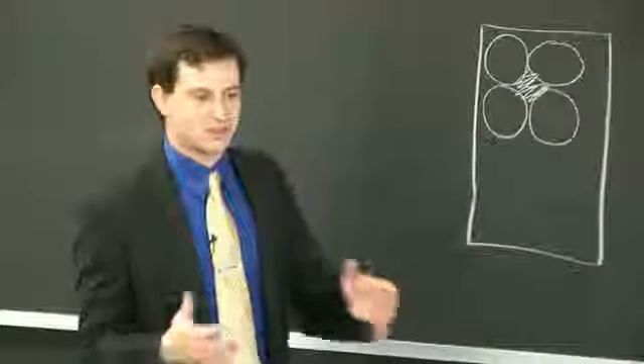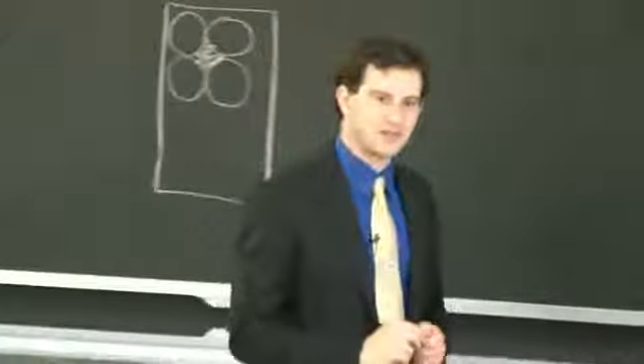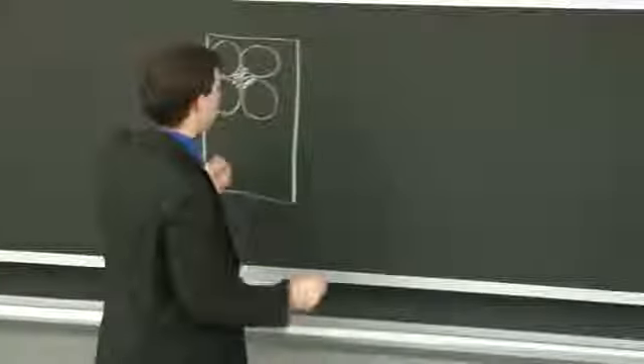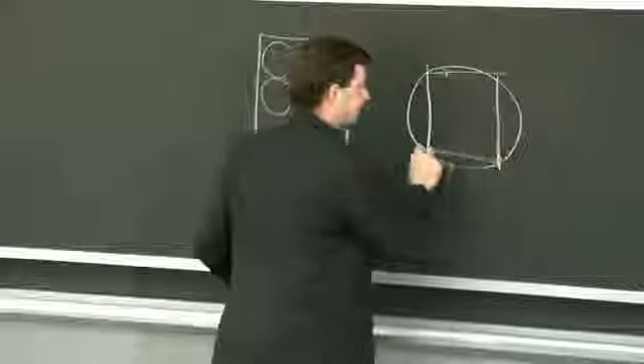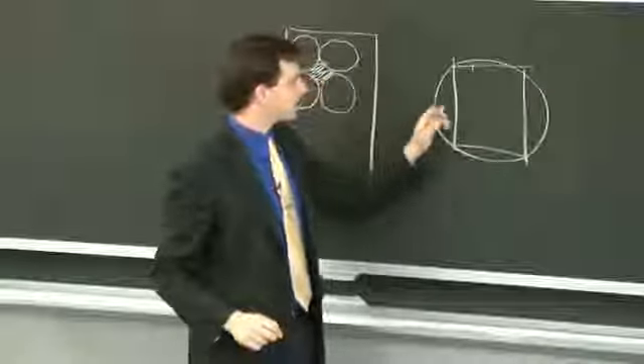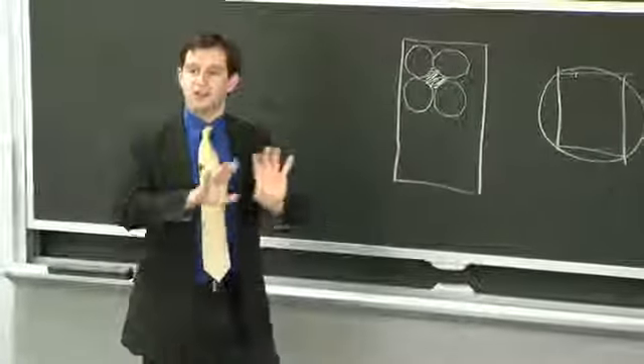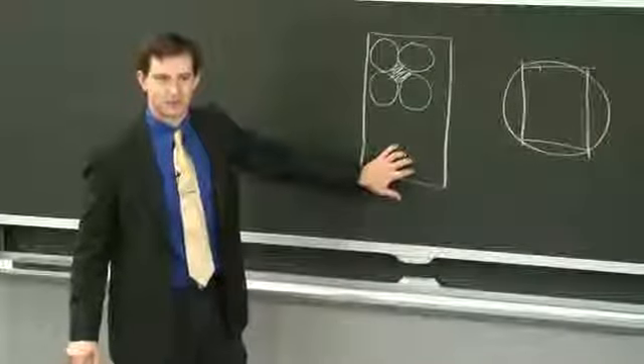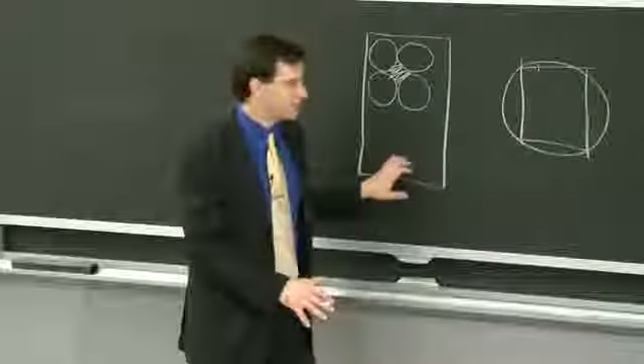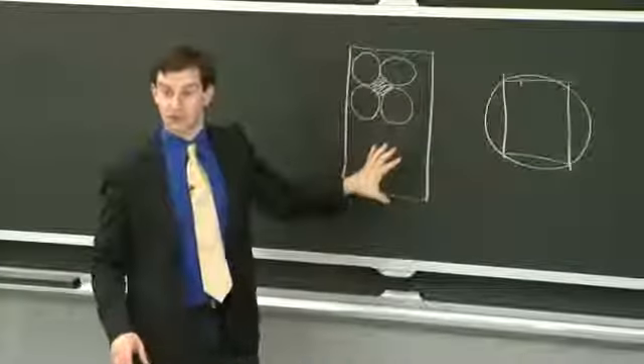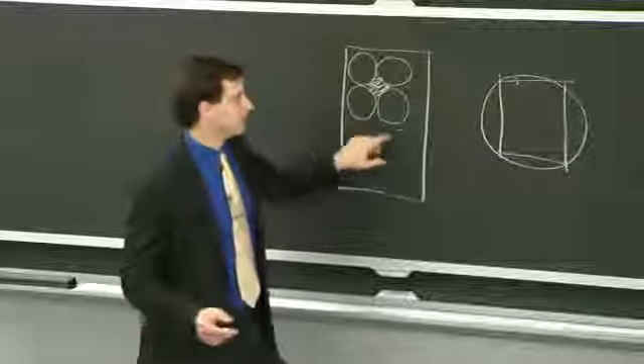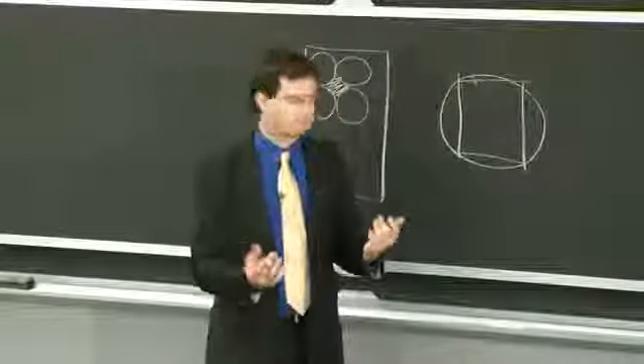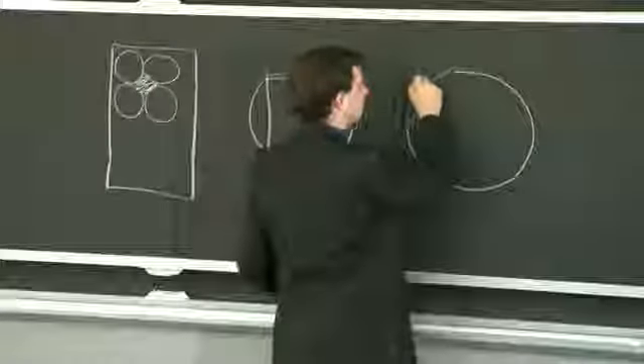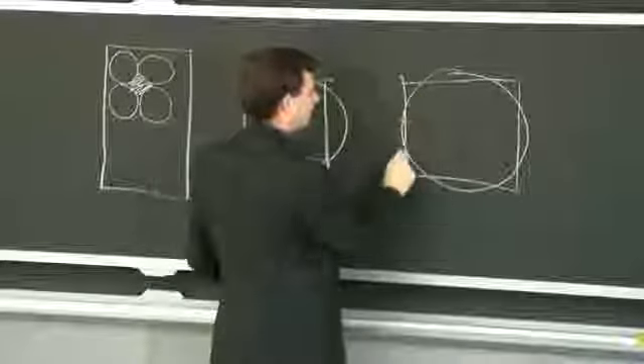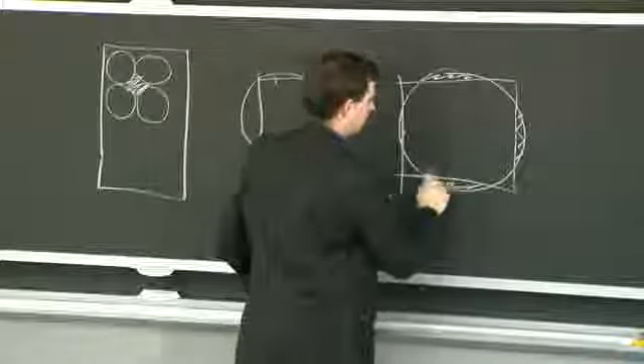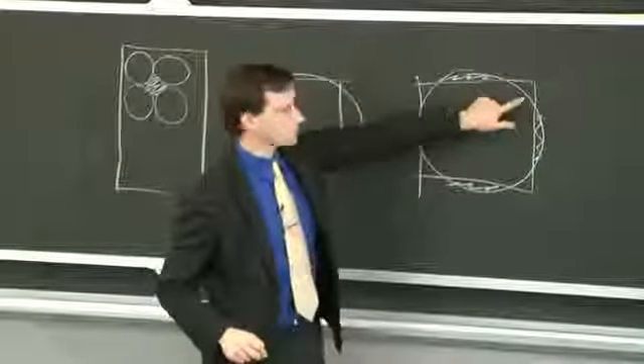Some of the earliest PV modules actually use circular wafers. But the more modern ones, what they do is a very complicated cost analysis where they say, OK, if I were to chop off the edges of my wafer and completely remove them, I'd be losing a lot of silicon, but I'd be increasing the packing fraction. So in the limit that my module materials, the glass, the encapsulant, the framing materials, are infinitely expensive and my silicon costs nothing, I want to do this. In the limit that my module materials are free and installation is free, but the silicon is super expensive, I want to keep full round wafers. And the reality is that we're somewhere in between. And so instead of making one or the other extreme, typically what you'll see is something like this chopped off, like that, where you have a pseudo-square. The wafer itself has flat edges on the sides, but it also has kind of pseudo-rounded corners here.